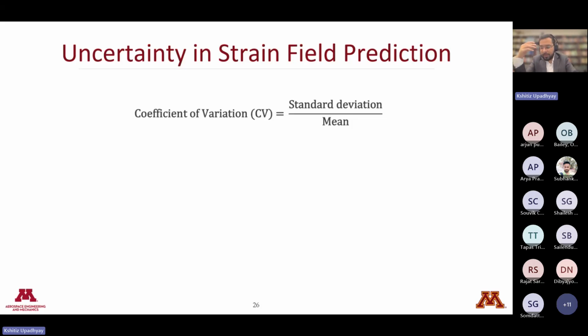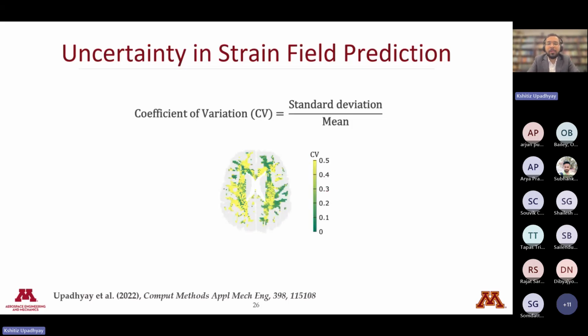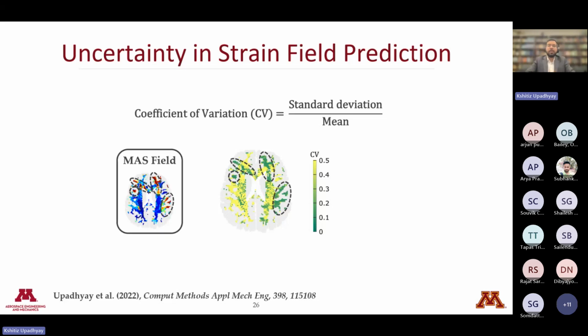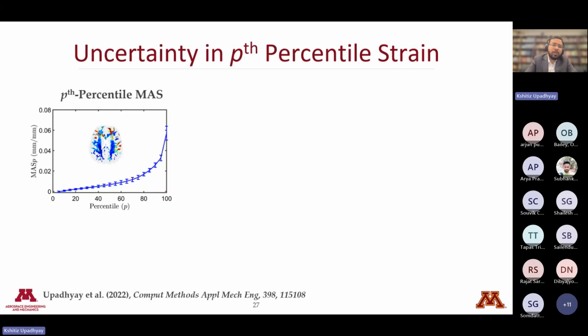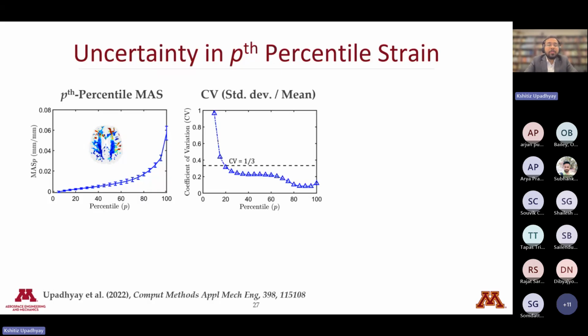So now that we have the surrogate model, we can run it tens of thousands of times. So we did it, and calculated the coefficient of variation, which is a measure of uncertainty across the strain fields of the human brain. Here, the green regions are regions of low uncertainty, the yellow regions are regions of high uncertainty. And we found out that the regions of low uncertainty also correlate with the regions of large strain in the brain. And what this told us is that when we investigated the uncertainty of different percentile strains.